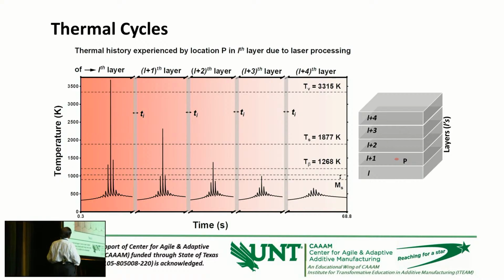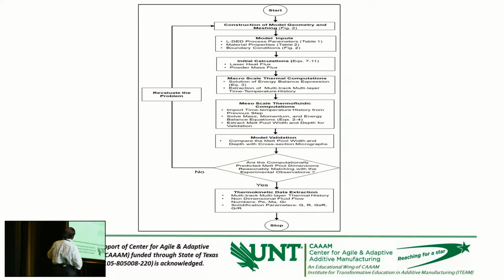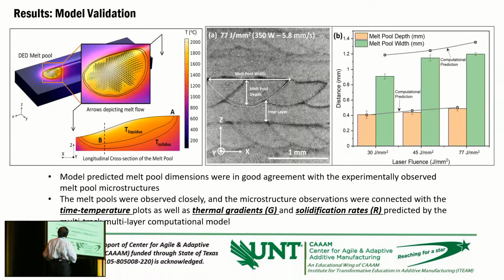So all those things depend on the process parameters and the material properties, and you can predict how often and how high a temperature this point would experience while depositing these layers. So all this is built into this program, and you can predict the temperature at any point in any layer, the thermal cycles it will experience, and then you can predict what phase transformations or what grain size or grain development will take place at that point. So let me show you some of this kind of model.